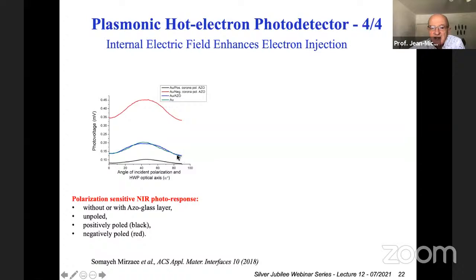That means that the hot electron emission is not affected, which is understandable because first, the electrons are not traveling through the capacitor, they are traveling from the gold to the ITO. So if you put something in the capacitor, it can change only the dielectric constant, but the layer being very thin, it doesn't change significantly the capacitance of our capacitor. So actually the photovoltage keeps being constant. If you want to understand what exactly the photovoltage in a capacitor is, it's the quantity of charge per unit surface that was generated divided by the capacity. So the photovoltage is just Q divided by C, which gives you a voltage that we detect.